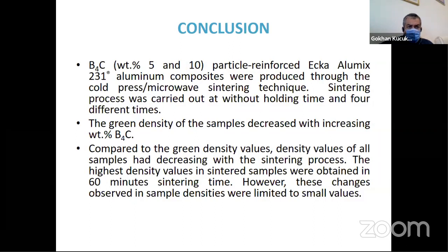Conclusions were achieved in this study. Boron carbide particle reinforced Eka-Alumix 231 aluminum composites were produced through the cold press microwave sintering technique. The sintering process was carried out at without holding time and 4 different times. The green density of the samples decreased with increasing percentage by weight of boron carbide. Compared to the green density, the values of all samples decreased with the sintering process. The highest density values in sintered samples were obtained in 60 minutes sintering time. However, these changes observed in sample densities were limited to small values.